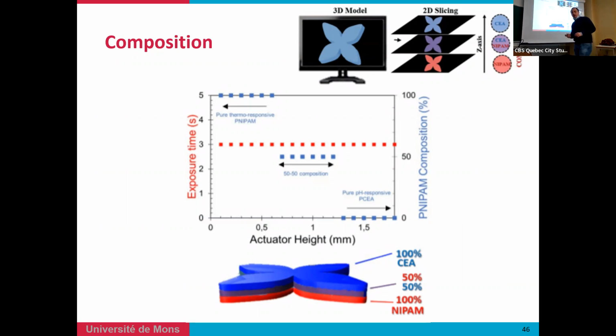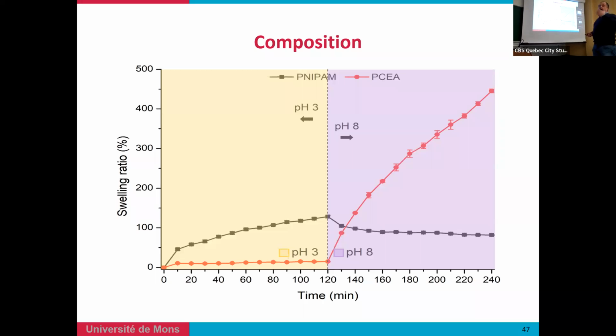Of course, we evaluate the pH response in the case of the pure polymer and the pure acrylic. You can see that in the case of the polymer, we don't observe any change, because we don't have any moieties able to interact with the pH.